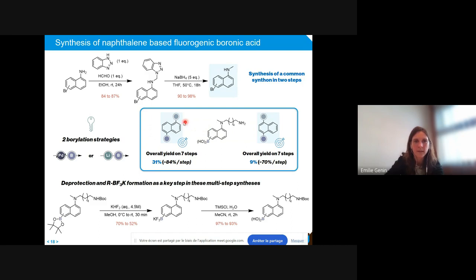The key steps were providing a key intermediate, a common synthon, in 2 steps, and then implementing different borylation strategies depending on the position of the 2 substituents. The last important point of the synthesis was to be able to provide pure and stable compounds, not so easy with boronic acid.